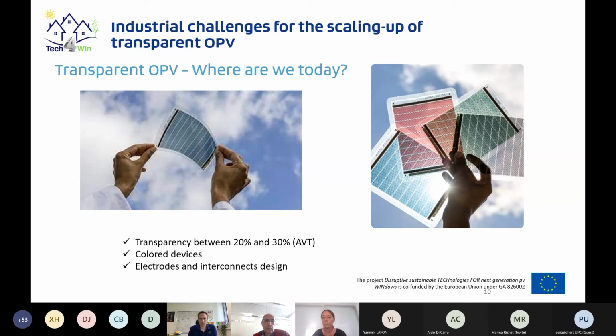And quite important thing is that we have a pattern of electrodes and interconnect design. So we can clearly see on the pictures that we have some blank lines and we have some patterns, meaning that the area of the device is not fully homogeneous, and there is some aesthetic loss in this kind of devices. So there are different challenges to overcome. Some are more materials based, so based on the layers and materials that are used in the stack, and the other ones are more process related.